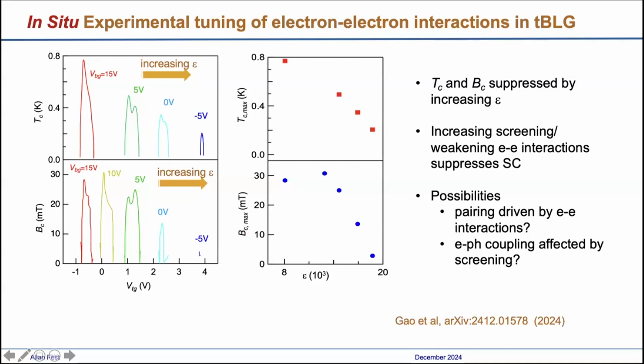Now we're replotting these domes at different back gate voltages, their extent in top gate. This is TC, the critical temperature dome, and this is the critical magnetic field dome. In the plot on the right, we pick the maximum value of the transition temperature, and then convert the back gate voltage and top gate voltage to the dielectric constant. What we see is that TC and BC are suppressed by increasing the dielectric constant, which means that increasing the screening, or weakening electronic interactions, suppresses superconductivity.